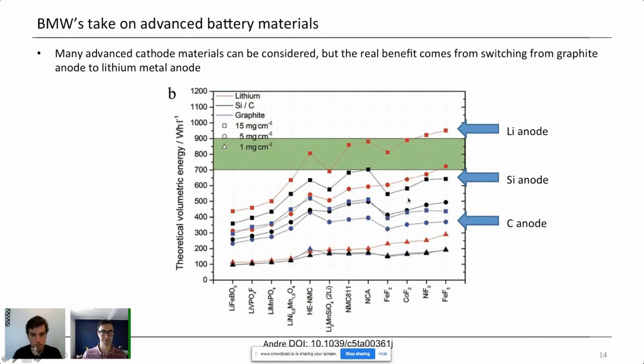So the two that are most popularly being considered are silicon anodes. And silicon then is the host material for lithium in a silicon lithium-ion battery. It is able to store lithium more densely than graphite can. And so that is, in short, why you can get improved energy density. BMW highlighted this green range here as what they're targeting for mass market electric vehicles.